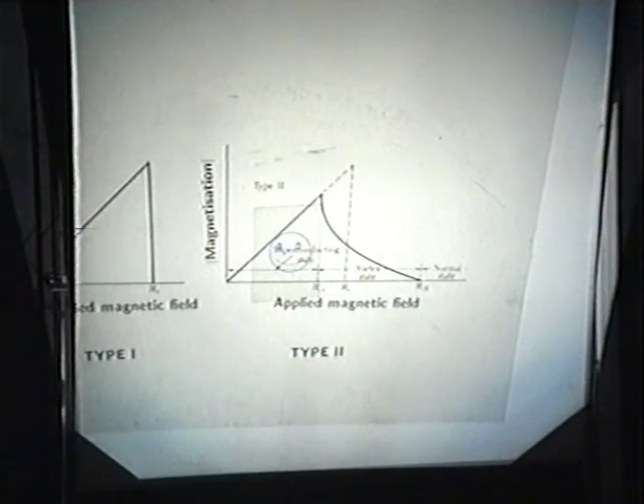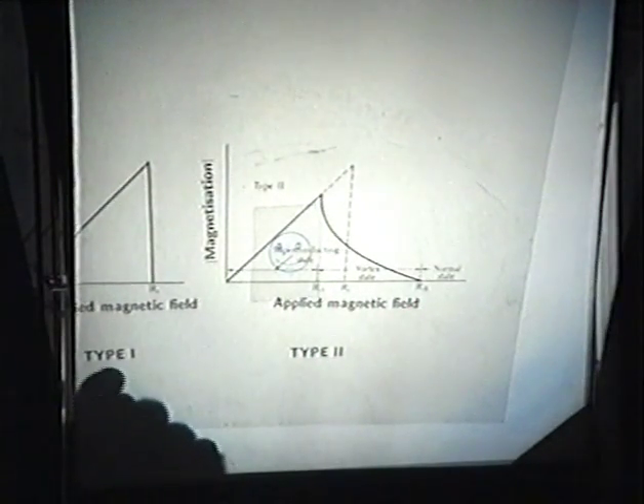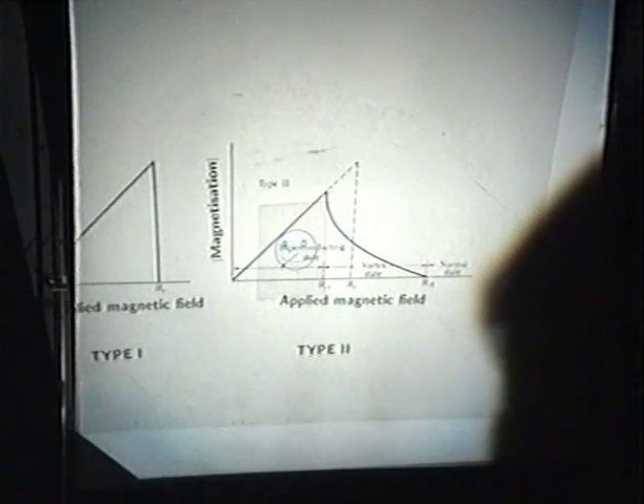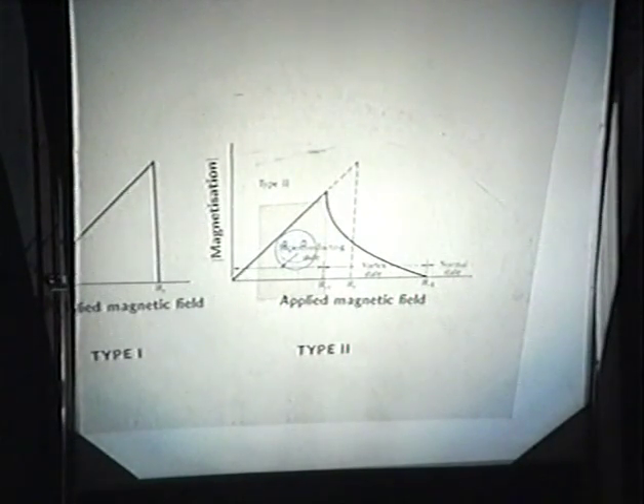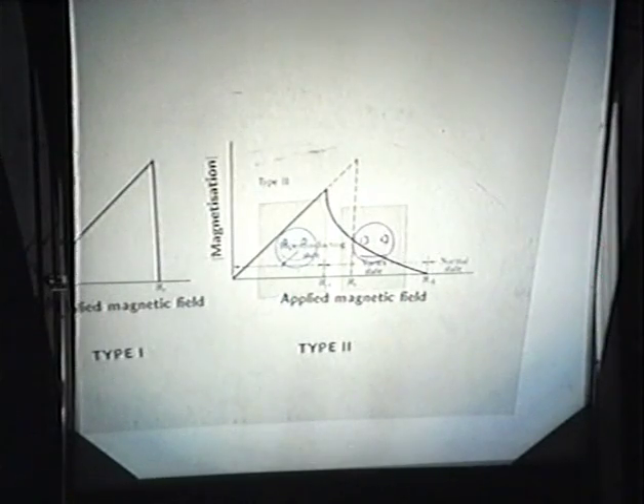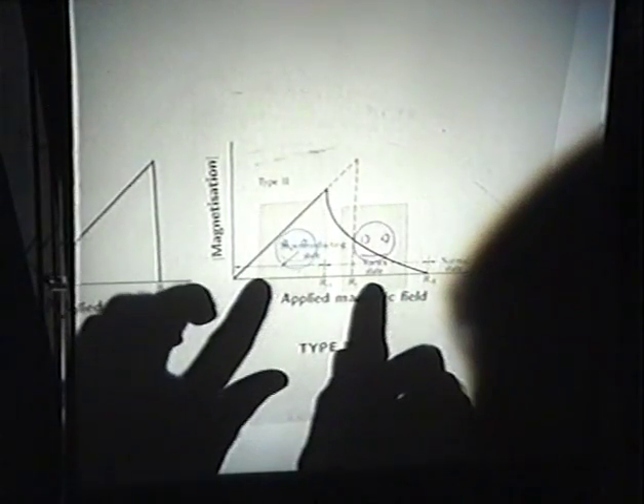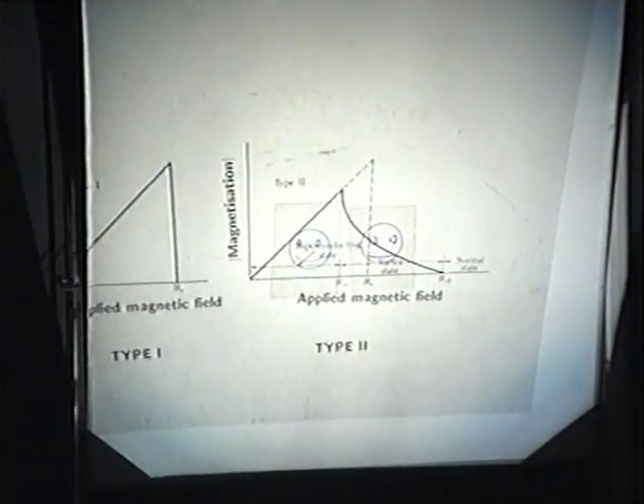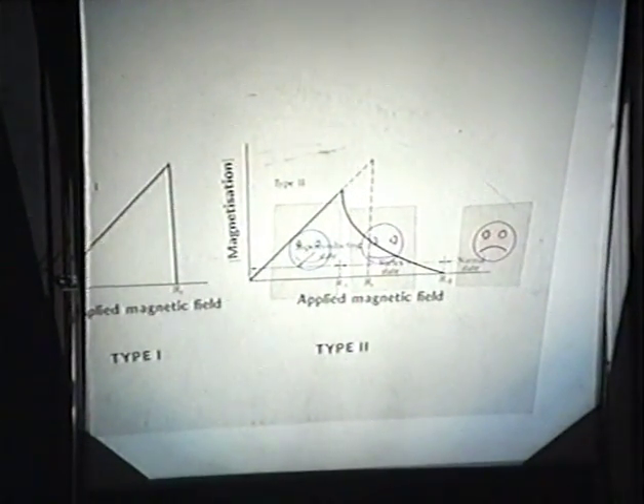It begins to get overwhelmed, but instead of collapsing in a heap all at once like the old type 1 did, it actually lets some of the field in. It lets some of the field in, and sacrifices some of the superconducting state into the normal state, but there's still sufficient superconducting state left that it still has zero resistance. And so we have what's called the vortex state, which is what happens after you lose the pure superconducting state, until finally you keep raising the external field until even then the vortex state can't hold the field anymore.